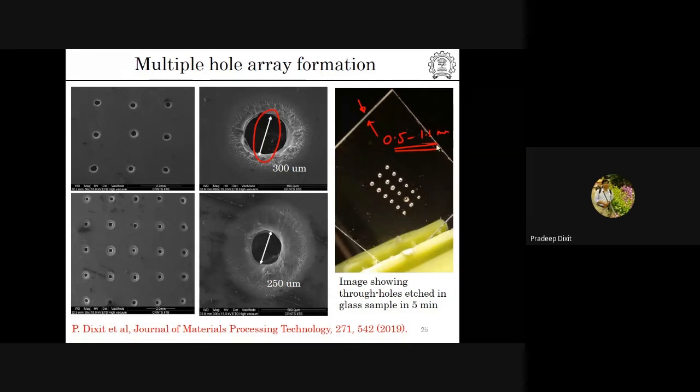Now what is the major thing? The main thing is that the time taken to complete this process is less than 5 minutes. The process is very simple. It does not utilize any expensive consumables; it only requires sodium hydroxide or potassium hydroxide as an alkaline medium. The required voltage varies from 40 to 60 volts. So there is no expensive consumable compared to the plasma etching process, and the equipment is also very simple. That is the major thing.